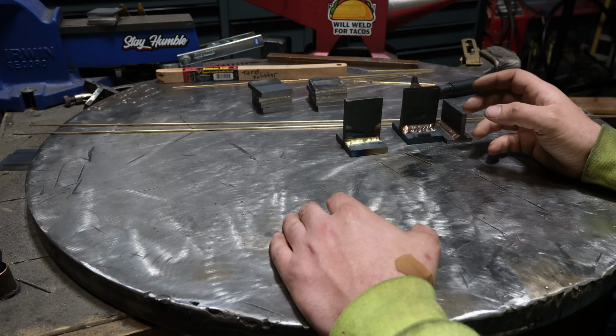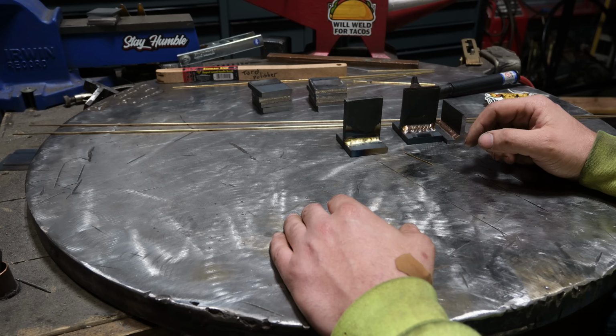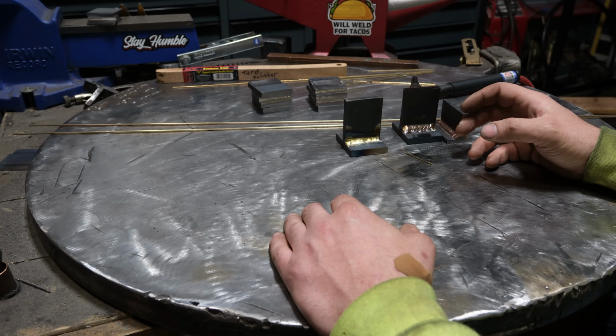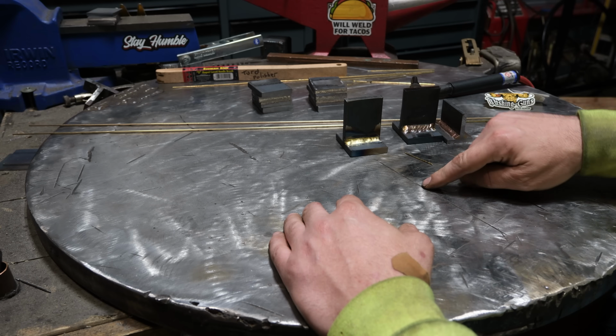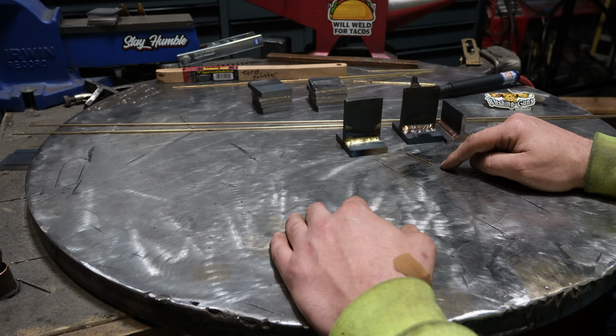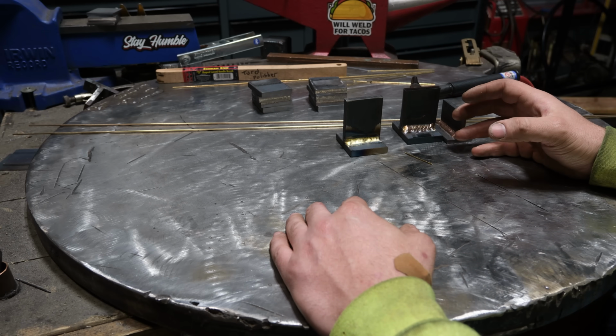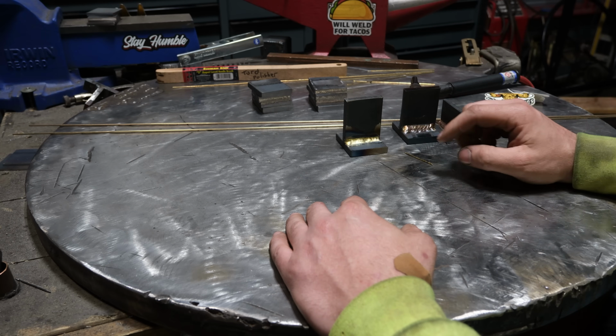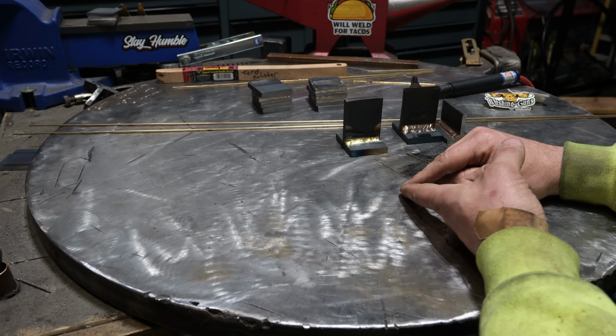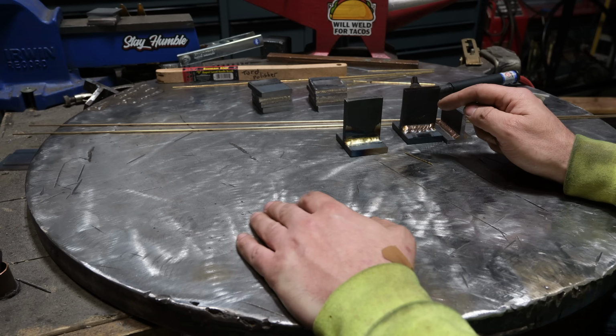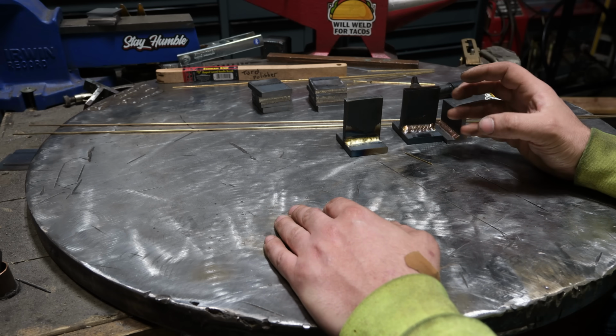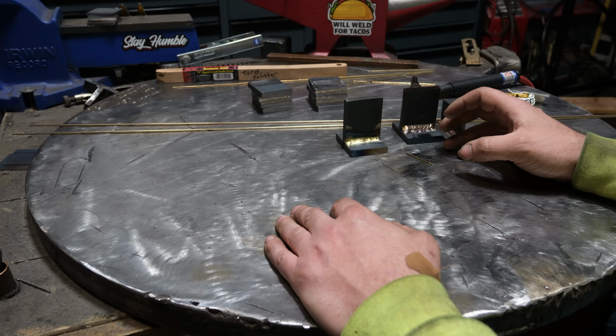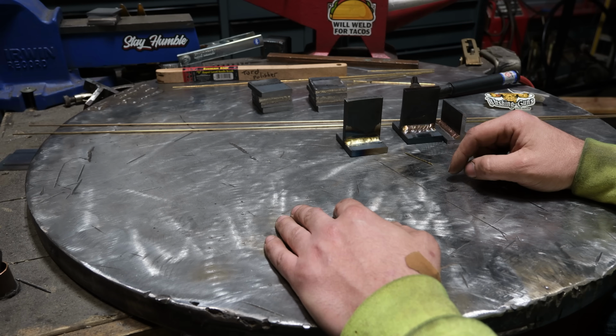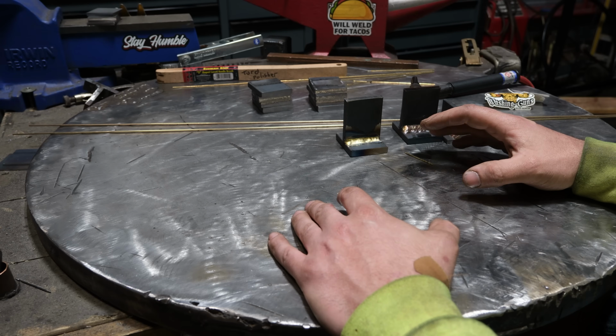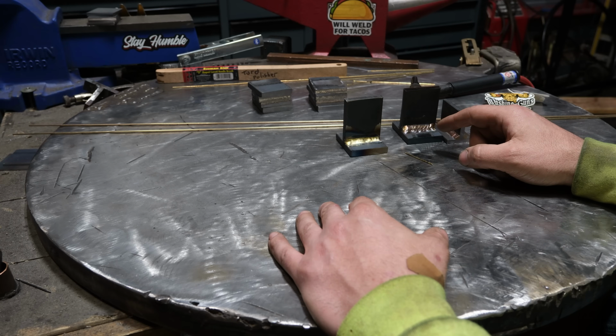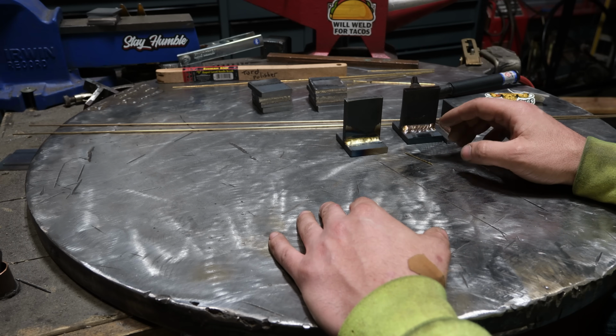Another potential use for this stuff is on a heat-sensitive alloy, like chromoly. Certain forms of chromoly do not like to be heated very hot, and they don't like to be welded, where it brings up the temperature to molten, super hot, and cools really fast. Those types of alloys, and it's not just forms of chromoly, but tool steels and all sorts of stuff, you can use this stuff, and because again you're not melting the base material, and you can control heat input, aka you're putting less heat into it typically than welding, it can give you the ability to join those materials stronger than a weld would be, because with a weld you have a heat affected zone that's far bigger, you have base metal dilution, you have all those things. Brazing can solve that issue of heat sensitivity and heat affected zone problems, all of that grain structure in certain materials.